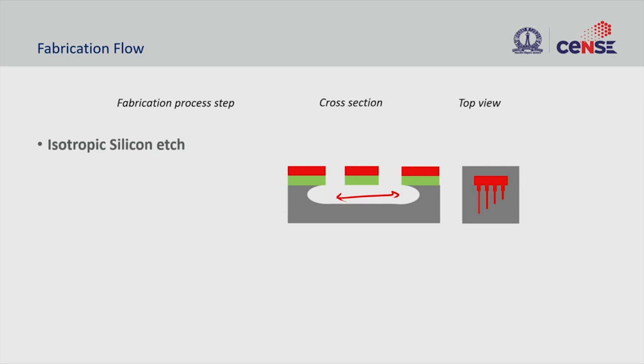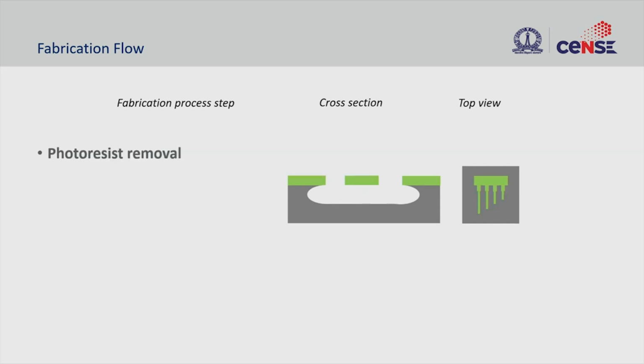Also by using dry etch, we will use a different chemistry, SF6 chemistry, in order to remove the underlying silicon using an isotropic process. Once this is done, we have these cantilevers that are freestanding. But it is not done yet because we still have photoresist present. We have to remove this photoresist, and the photoresist removal can also be done using a dry process. We can use oxygen plasma in order to remove the photoresist.